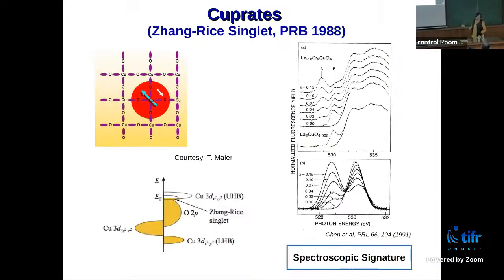A concrete example of that are the cuprate superconductors. In this case, the copper is 2+ and d9, and therefore you have one hole at the copper site. Now, if we dope this material, by which you get the superconductivity, we introduce an additional hole by hole doping. But this hole, instead of going to the copper, actually goes to the oxygen and therefore makes a singlet pair. So the hole at the copper site and the doped hole that goes to the oxygen give rise to a very famous concept like the Zhang-Rice singlet.